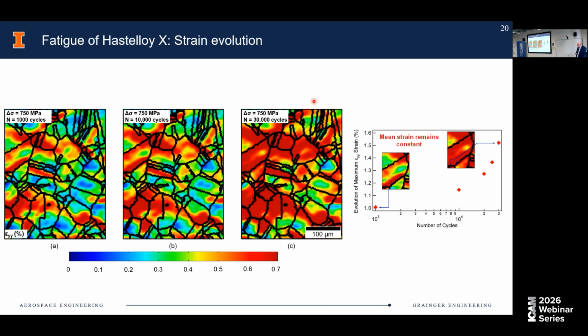Same thing for fatigue. Here's a similar kind of thing for fatigue: 1,000 cycles, 10,000 cycles, 30,000 cycles, and again you can see, first of all, the inhomogeneity, obviously, as expected, and then this increase in strain. How does that correlate to damage? Ultimately, that's really what we want to look at.